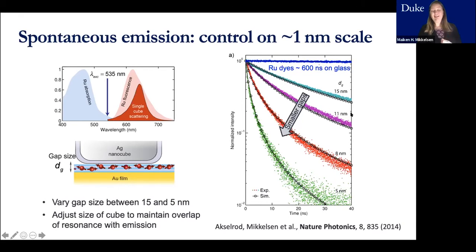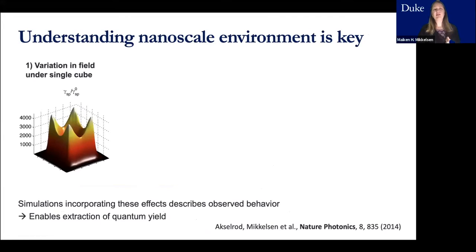So that, I think, was very exciting, because these were dimensions that had not really been carefully explored in the past. And we can see, compared to the intrinsic lifetime of these ruthenium metal complex dyes in glass, which looks almost flat here, these are very large enhancements. But we also found that understanding this nanoscale environment is key.